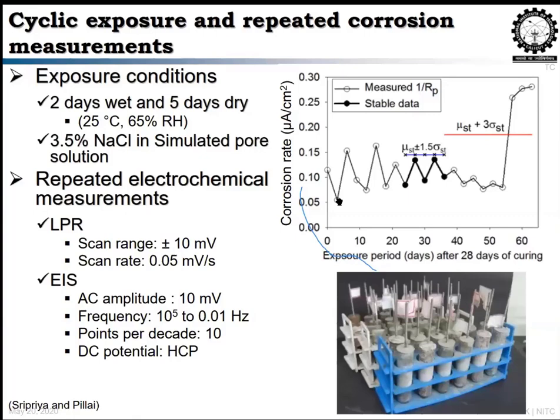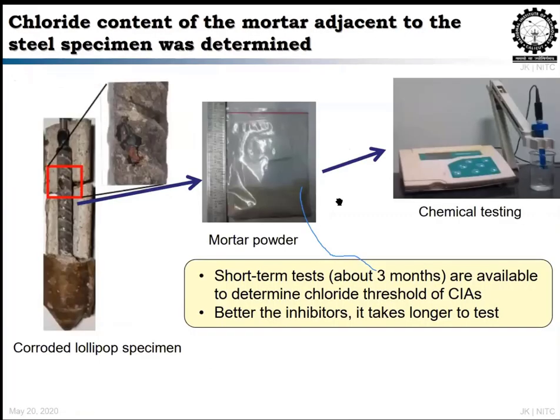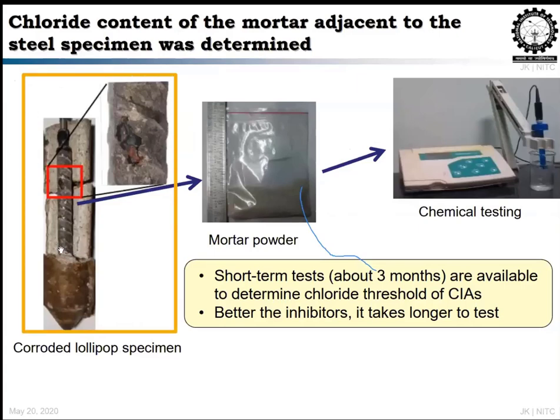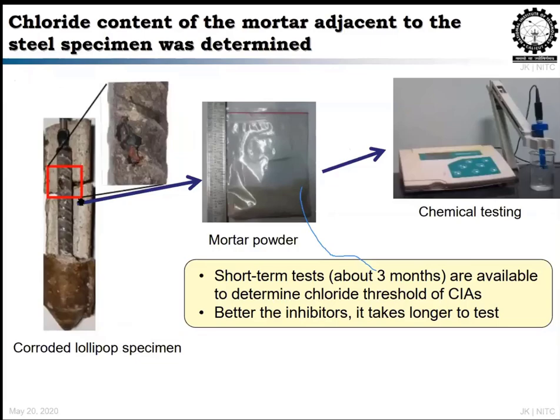So all those things you can find with the test procedure which is available. Here, what we do is we find exactly how much chloride is required at the steel surface, where the corrosion has occurred. If you consider this specimen, at the left corner marked as a red box, we will collect the mortar specimen and find the chloride concentration.